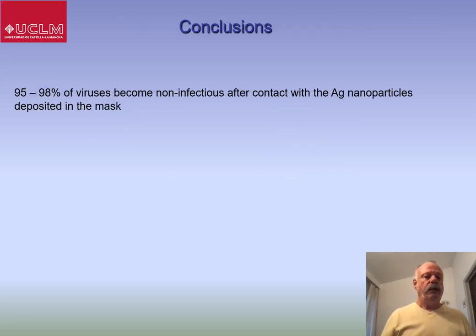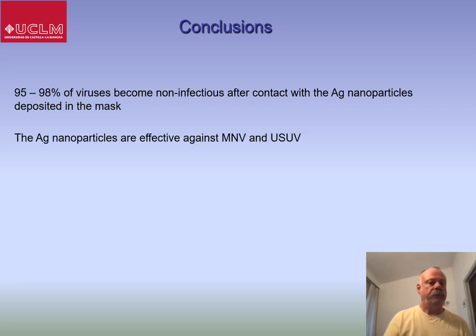So with that, general conclusions are 95 to 98% of viruses become non-infectious after the contact with the silver nanoparticles deposited in the mask. The silver nanoparticles are effective against both the murine norovirus and the Usutu virus, and this is interesting because it seems to show the effect is generic, because in the two cases they're interacting with completely different proteins.